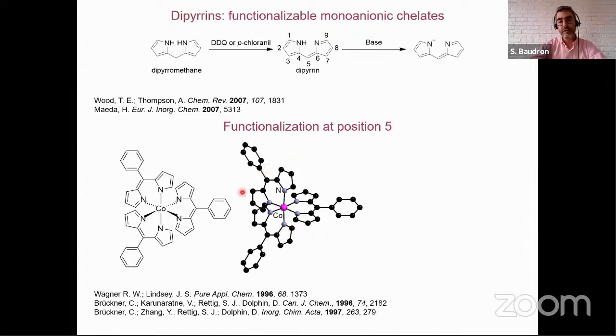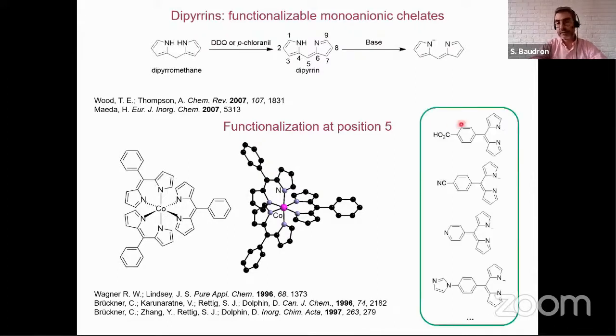And we saw here the aromatic ring as a platform to introduce a secondary coordination site to develop differentiated ligands. So you can see here examples of such ligands, dipyrrinato ligands bearing a benzoic acid group, a benzonitrile, a pyridine, or a phenylimidazole. And playing with those ligands, one can envision to construct coordination polymers.